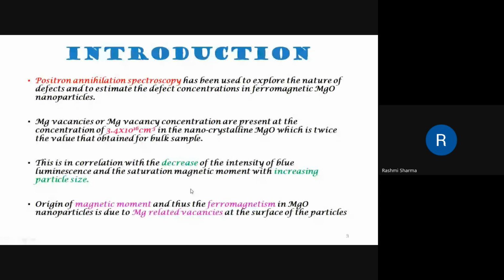This correlates with the vacancy concentration of the magnesium oxide nanoparticles. So after all this positron annihilation spectroscopy and optical spectroscopy, what they found was that the origin of magnetic moment and the ferromagnetism in magnesium oxide nanoparticles is caused due to the magnesium related vacancies present at the surface of the particles.